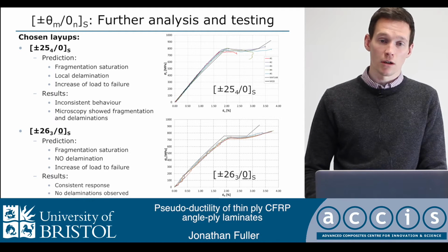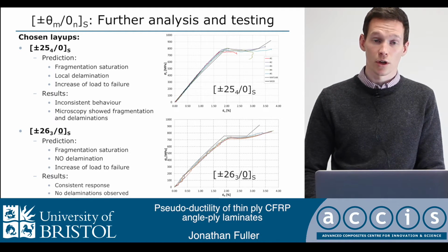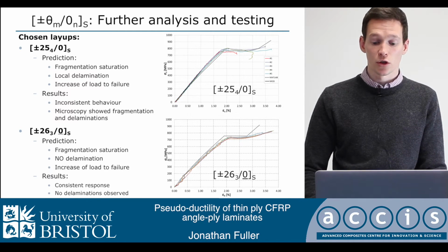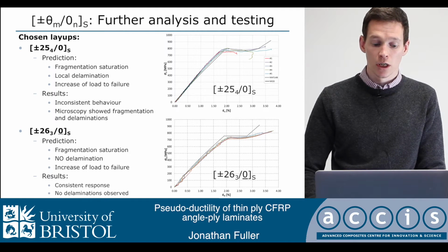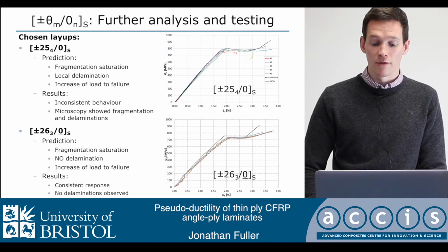And just by changing the fiber angle and the number of zeros, so the ratio and the absolute thickness, we can change the behavior. So the top is showing fragmentation and local delamination around those fractures, and then the bottom graph is behavior which shows no delamination and purely fragmentation. And obviously you can see here there's some inconsistency in the results, but overall the analytical modelling gives a very good prediction of the response that is actually seen experimentally.